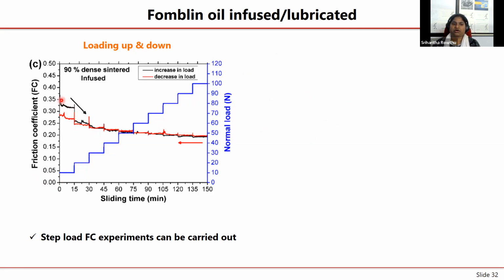But then there may be a question about, in the beginning of the sample, in the beginning of the experiment, there will be something called running-in stage. What if this running-in stage is not taken into account? And that's why, to explain that, the first test was done by increasing the normal load from 10 to 100 Newton.